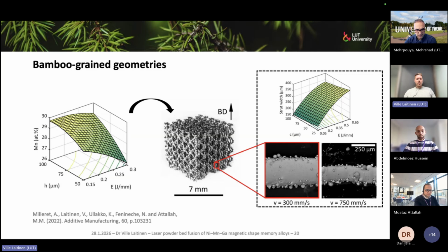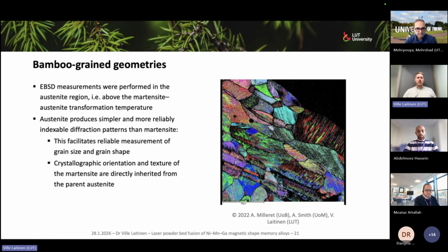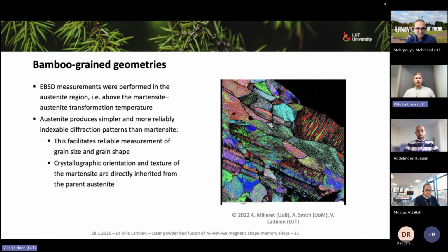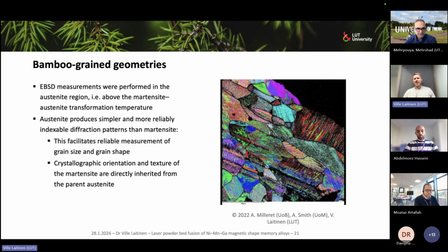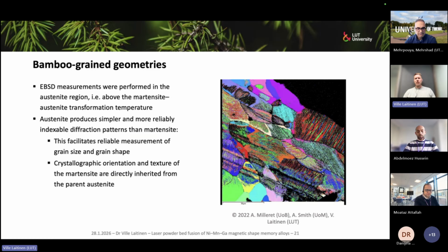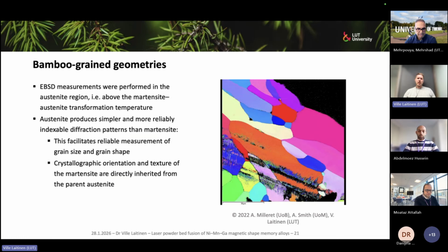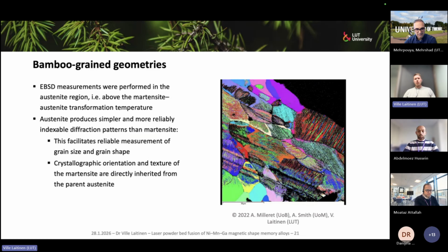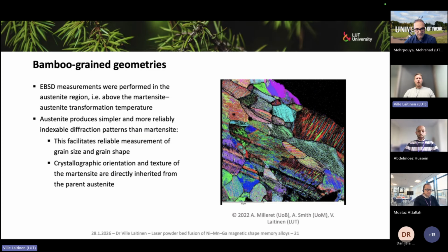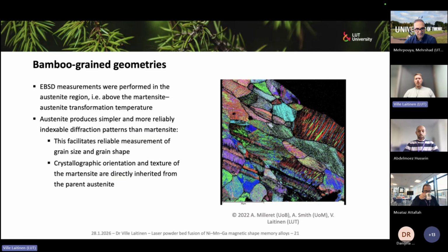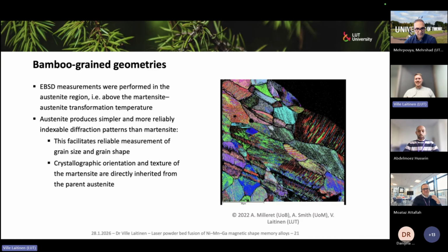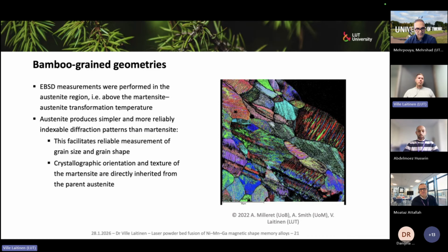We first show how we do the measurement itself. We have high temperature EBSD. The reason we use high temperature is that we want to do these measurements in the austenitic phase. Martensite makes a very complex diffraction pattern, which is first very difficult to index, but second, it's very difficult to determine what is a martensite colony versus what is an actual grain boundary. So by heating, we can reveal the real grain structure. The advantage is that the crystallographic orientation and texture of the austenite is perfectly correlated to the martensite. There's only a 0.3 degree deviation in the axis direction, and it's nearly the same from the actuator point of view.